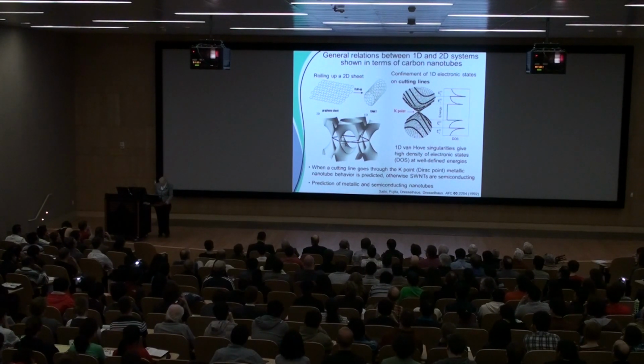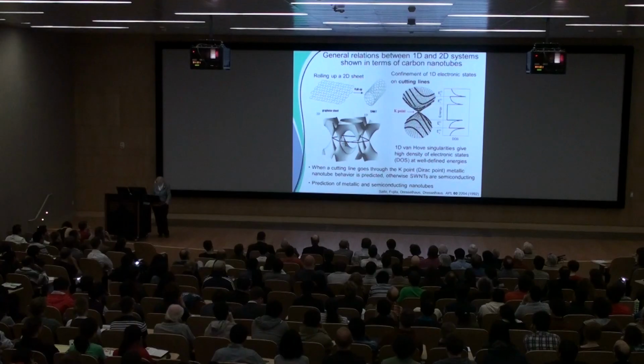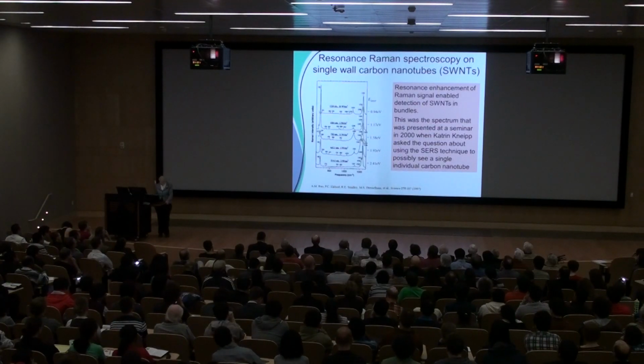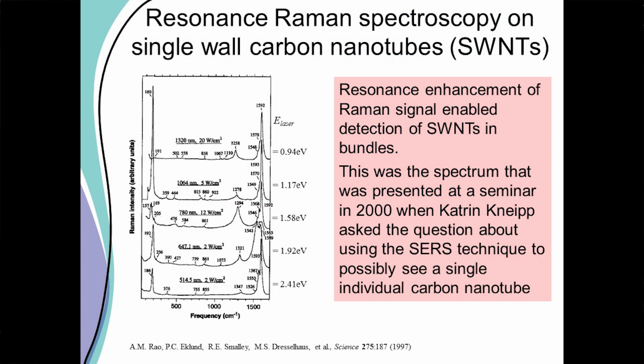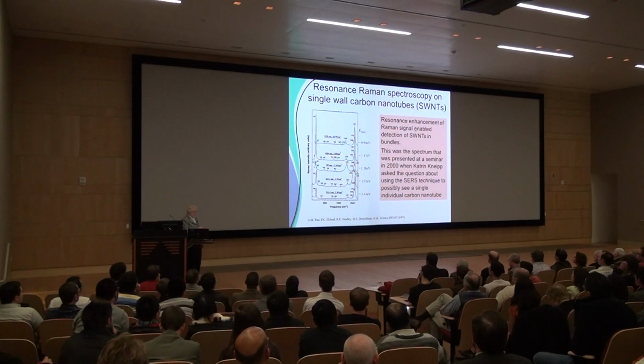Yes, this is correct. Then the field took off, and everybody in this room practically has heard about semiconducting and metallic nanotubes, so this is well known now. But it wasn't at the time, and we had this simple, very simple theory, but it took a while to get going. The first spectroscopic studies actually was done on a sample that had 1% nanotubes in a carbon material. And we could see a signal. It was very, very poor. And the people in the journals didn't like it, but we did get it published in 1994.